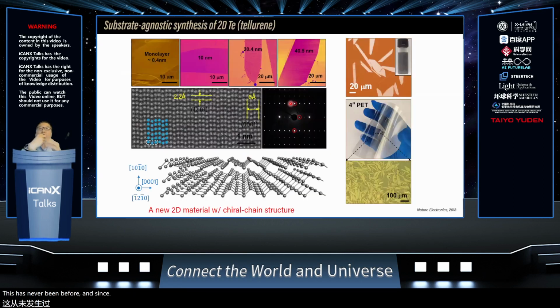Since then, we were able to expand that growth and transform that one-dimensional growth into a fully two-dimensional growth, getting atomically thin tellurium flakes with controlled thickness and very large lateral dimensions, ranging from tens of microns to even hundreds of microns, using an aqueous solution method without using any substrate. So we can prepare these tellurium flakes in water solution and transfer them onto any substrate afterwards. The TEM analysis shows that the obtained flakes possess a very clear chiral chain structure of tellurium.